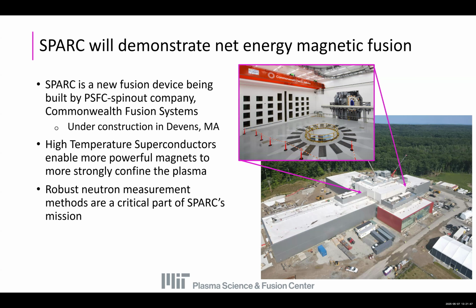So SPARC is designed using high temperature superconductors, which, like Angus mentioned, is sort of the key technological breakthrough that's enabling fusion to really take the next step. These magnets are more powerful than previous generations of magnets, and they confine the plasma a lot more strongly. So you're able to achieve higher temperatures and densities without having to put in a lot more power to maintain those densities and temperatures. And one of the key parts of SPARC's mission of proving that net energy is possible with magnetic fusion is having a really robust set of neutron diagnostics and neutron measurement techniques.